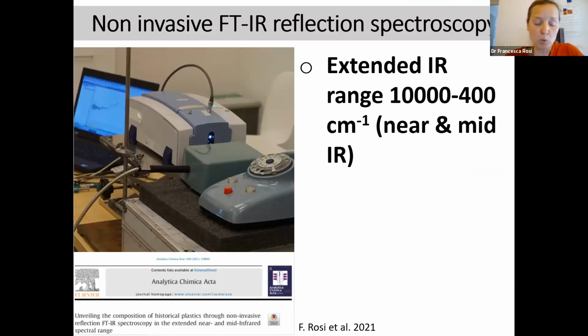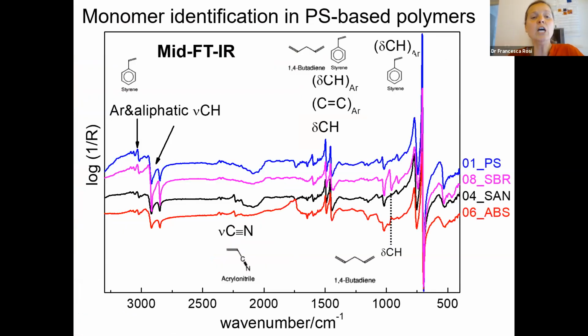In our study, we increased the knowledge by extending the explored spectral range for the plastic characterization to the near infrared, so covering the wide range from 10,000 to 400 cm^-1, with the idea of going beyond the simple polymer identification. In fact, we exploit the mid-infrared range, and you see here the derivative-like feature mainly following the behavior along the wave number of the real part of the refractive index, which we can associate with the different functional groups belonging, for example, to different classes of polymers, polystyrene-based polymers. So we can distinguish when polystyrene is alone, or when it is also with acrylonitrile, or with an acrylic, or when all the three are present in ABS.